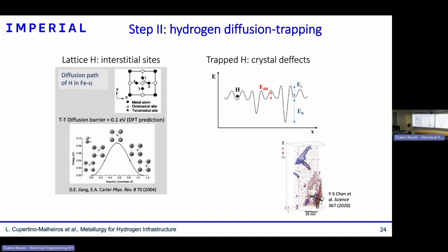There are some defects, basically where the atoms are not very well ordered and there is some space. On those spaces, hydrogen will tend to be attracted to them. If you think of an energy diagram, here the y-axis is energy, and x is the diffusion path of hydrogen. When hydrogen is here in the beginning at the interstitial site, there is a very small energy barrier. But also when hydrogen is in this interstitial site, it has smaller energy, but not that much smaller.